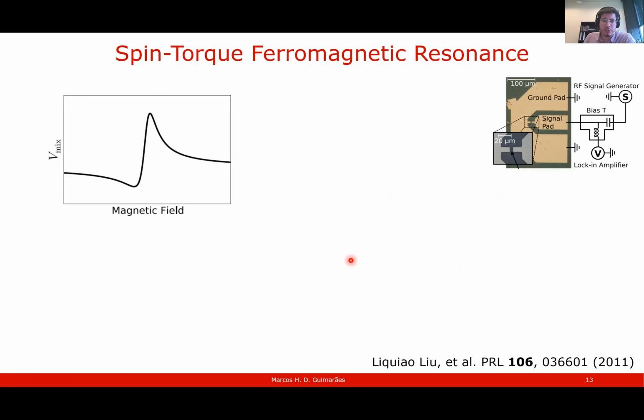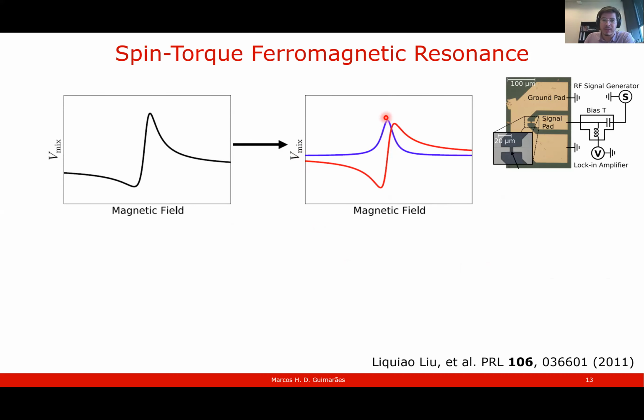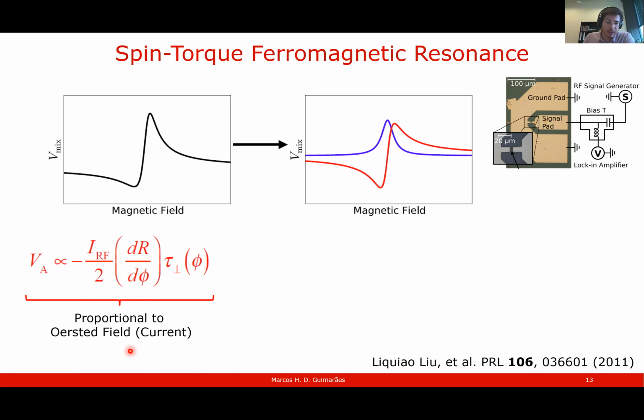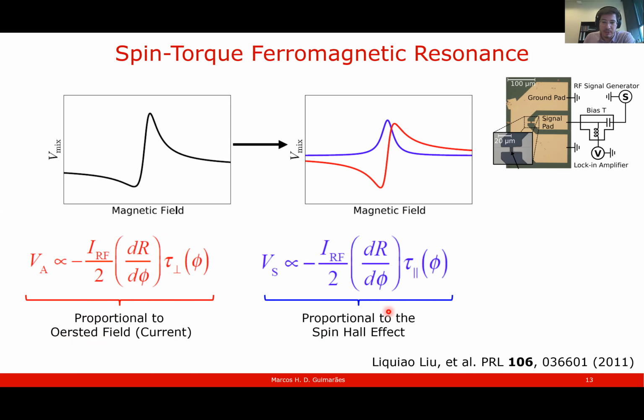And this shape is actually pretty nice because you can decompose it into two components: a symmetric Lorentzian that looks like this in blue, and an antisymmetric Lorentzian that looks like this in red. And they give you direct information on the torque. The antisymmetric Lorentzian gives you something proportional to the derivative of the resistance with respect to the angle of the magnetization, the current that you're applying, but most importantly, this antisymmetric component is proportional to the out of plane torques, which, if you recall, is mostly proportional to the Oersted field, for example, given by the current. Now, the symmetric component is proportional to the in-plane torques that, for example, could be due to the spin Hall effect.